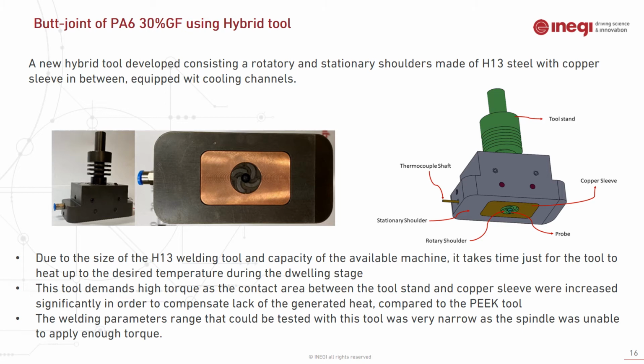An innovative welding tool was developed and tested. This tool is a combination of a rotating shoulder with a stationary shoulder. The purpose for that was to compensate lack of the frictional heat when using a stationary shoulder, because rotating shoulder has the main effect on generating frictional heat, and with the absence of a rotating shoulder, the welding tool suffers from lack of heat generation.